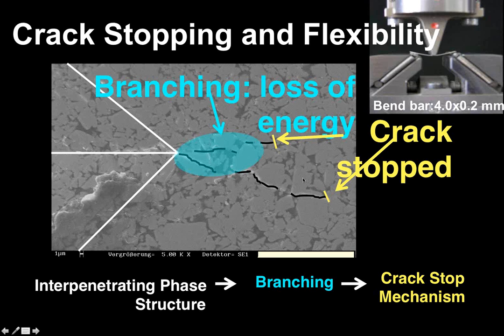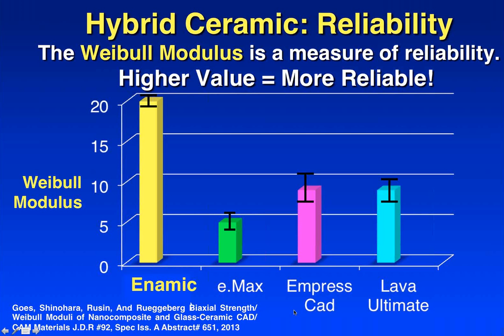There are lots of natural teeth out there with cracks in them. The idea is that even though you might generate some damage in the material over time, that material is damage resistant, so it lives another day. It doesn't have that catastrophic failure. And here's a bend bar over here. It's only 0.2 of a millimeter thick, and this is something you can never do with a ceramic, which would have been cracked into many little pieces by the time it reached that flexure value.